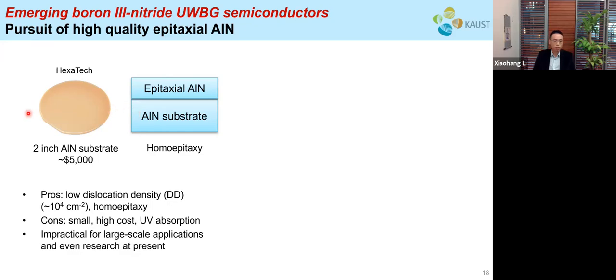The first one is the native aluminum nitride substrate. Basically it is the same material as the epitaxial aluminum nitride, so it does not have a lattice or thermal mismatch. Therefore you can have a very low dislocation density, about 10 to the power 4 for the epitaxial aluminum nitride. However, this aluminum nitride substrate has significant drawbacks as well. First, the size of the substrate is relatively small. Also, it's very, very expensive.